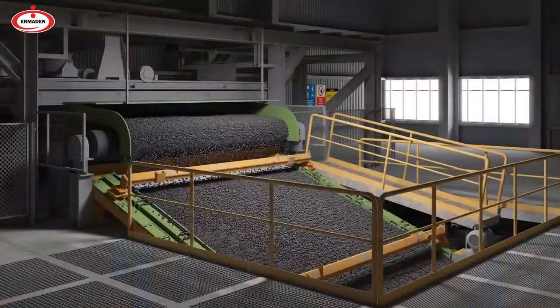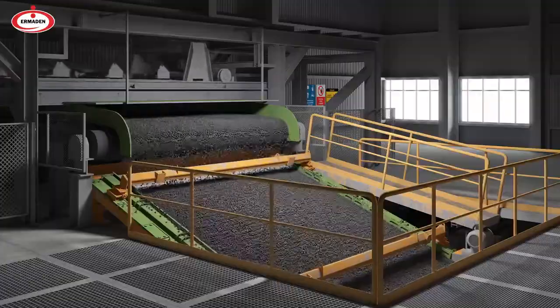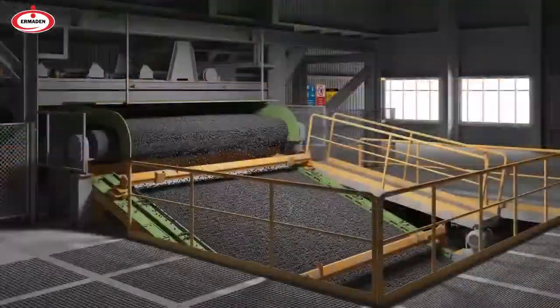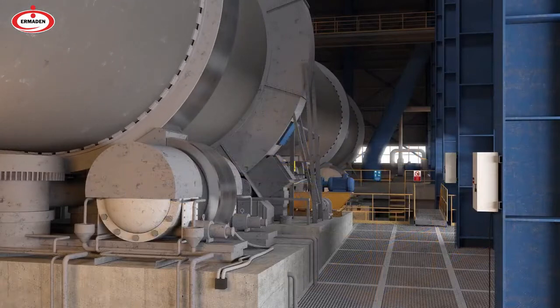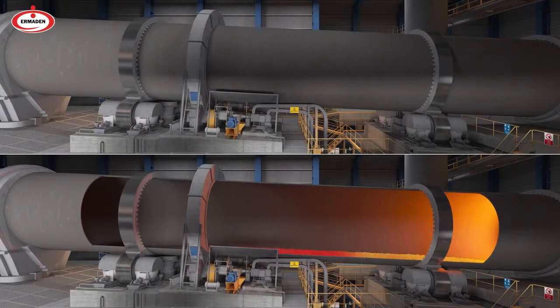The raw pellets are passed through the roll feeder in order to be sieved in the pelletizing unit and to correct their spherical forms. The raw pellets taken from the roller feeder are laid on the grills of the equipment called moving grill for gradual drying and preheating processes. In the moving grill, the pellets that are dried and preheated are fed to the rotary kiln.